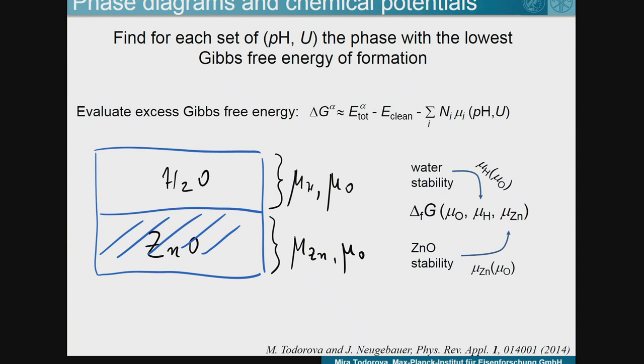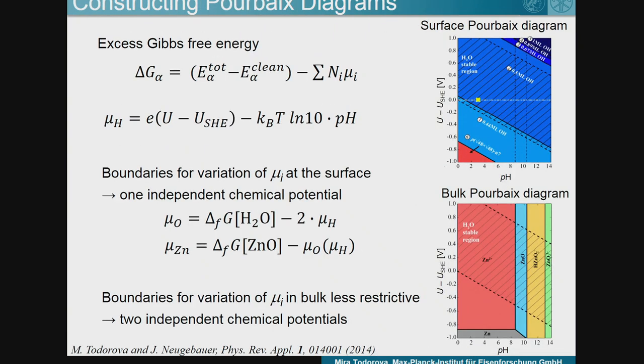Now, within this system, we do have a few chemical potentials we have to consider. The zinc oxide is characterized by a zinc and an oxygen chemical potential, while the aqueous system is characterized by hydrogen and oxygen chemical potential. So this means that we end up with a Gibbs formation energy which is dependent on 3 potentials, but because we have to account for the stability of both zinc oxide and water, we can see that both the hydrogen and the zinc depend on the oxygen chemical potential, so we end up with a situation in which we have just the dependence on the oxygen chemical potential.